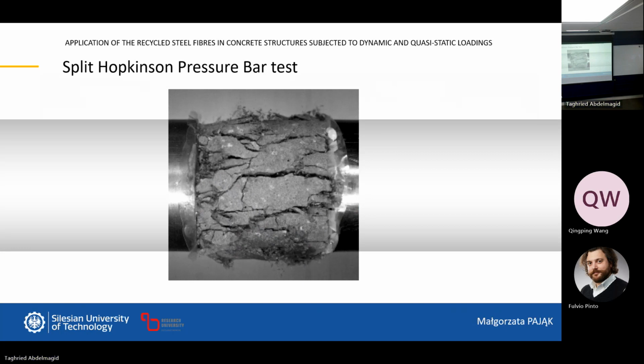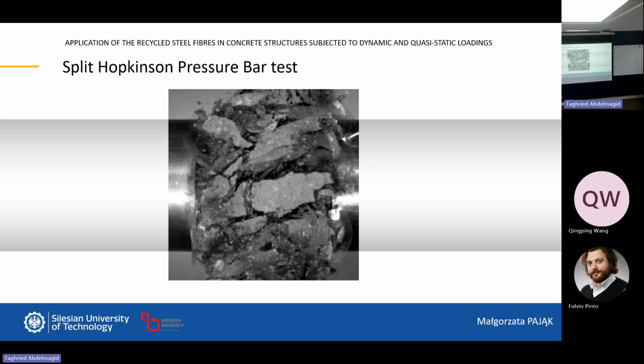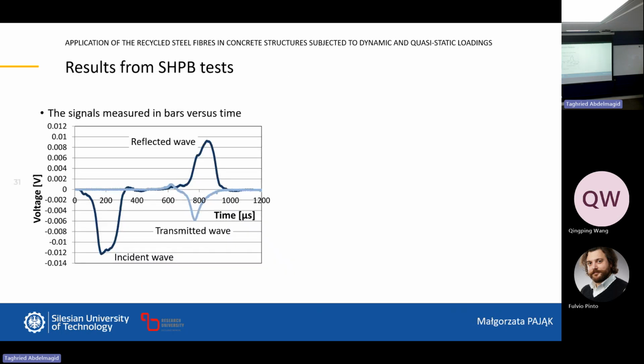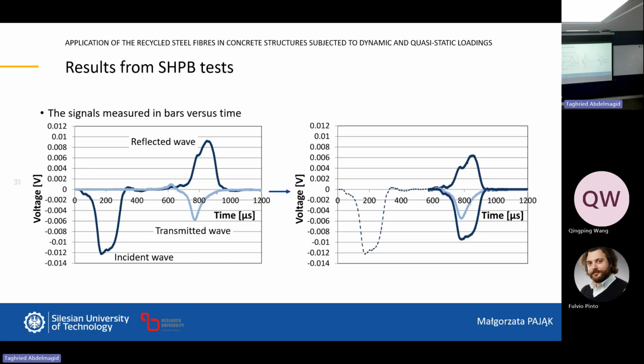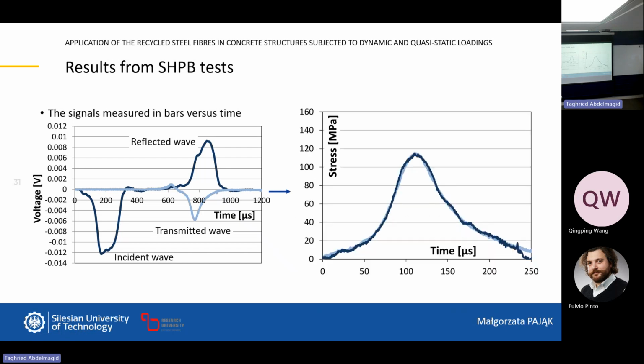It lasts microseconds. So now you can see how it's crushed, and to check whether the test is okay, this is what we get from the machine. We get the incident, reflected wave, and transmitted wave, and then we have to process it to check if we have the equilibrium stress state. In a compression test, we are not thinking about it because it takes time to compress it. It's a long cylinder, 150 in diameter and 300 millimeters in height, so it lasts about 2 to 2.5 minutes. So it's very, very long. Yes, so the specimen has time, and that's all.